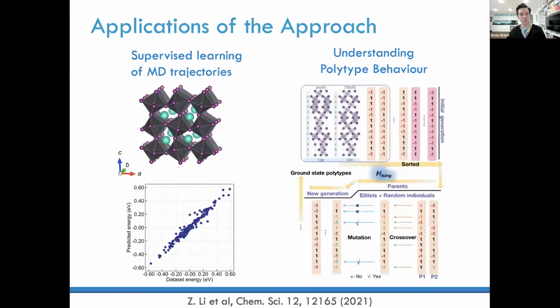There are some quite nice findings in that particular paper, but I don't want to draw on it too long. But what Kazuki found, quite surprisingly, and this is really thanks to one of the reviewers pushing us to do this, is that he performed a series of molecular dynamics simulations for some halide perovskites and found that a very simple supervised model that just tried to reproduce the energies from the MD, a really minimalist model where the only features were the distortions of the octahedra, did a very good job. So with 4 dimensions, you could get a very good fit to the energies.